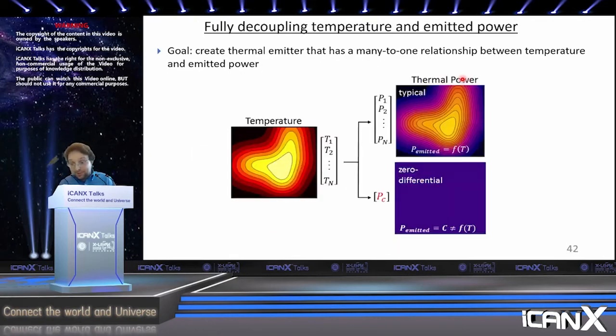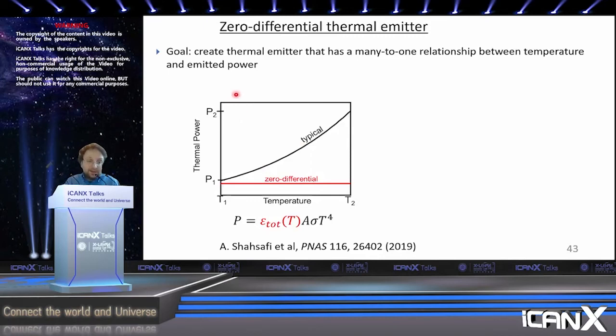You can imagine that infrared cameras are going to become more and more commercially accessible and cheaper and more ubiquitous, and you want to have a way to conceal some information from them as a countermeasure, if you like. So the idea here would be that the thermally emitted power, integrated over the relevant wavelength range, versus temperature, instead of increasing with temperature, is just a constant line and therefore has a zero derivative. And so the only way to do that is to have an emissivity that's temperature dependent in just the right way, so that the power remains constant. Therefore, this total emissivity needs to have roughly a temperature to the minus fourth dependence. It's not exactly true, because in some cases you're limited to a finite wavelength range, but roughly speaking, this needs to be 1/T^4.